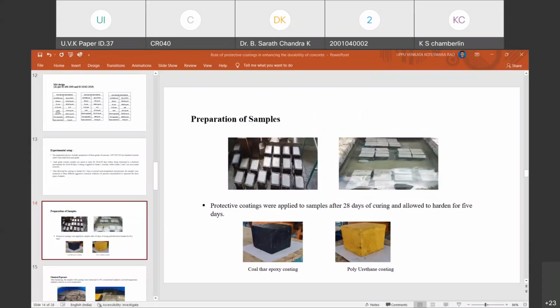Please continue. Okay, sir. This is the preparation of the samples, and these are the two protective coatings. I have used coal tar epoxy coating and polyurethane coating. I have coated two layers: one layer of 200 micron thickness, and another layer also 200 micron thickness, a total of 400 micron thickness. And this is the polyurethane coating.